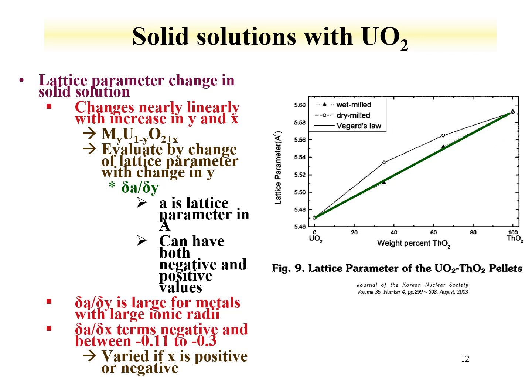So for something that's 50%, the lattice parameter would be a contribution of 50% of the uranium dioxide and 50% of the thorium dioxide. This is a way, if one takes a compound as a solid solution and measures the lattice parameter with X-ray diffraction, you can determine the composition of both. So this linear change is Vegard's law.